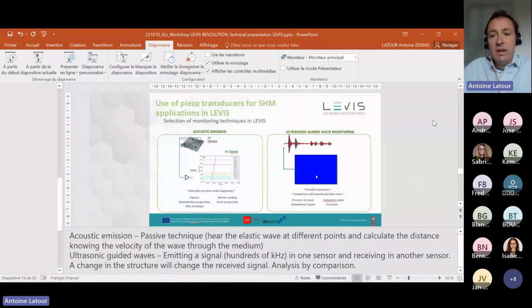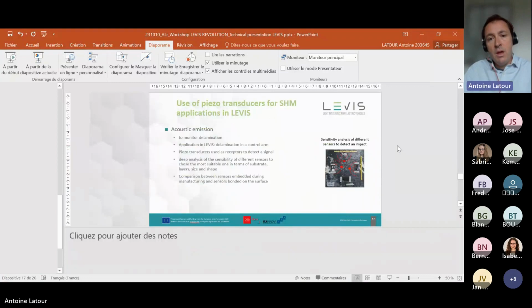The other technique is the ultrasonic guided wave monitoring. In that case, we are using transducers as sensors and emitters. We emit a signal in the hundreds of kilohertz range, and we receive the signal with some other transducers, and we can compare the signature between the signal acquired with a baseline state. So we can monitor quite the same type of events like cracks, delamination, debonding, and even corrosion.